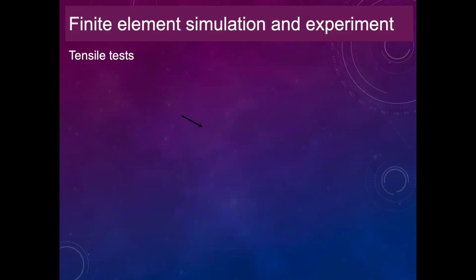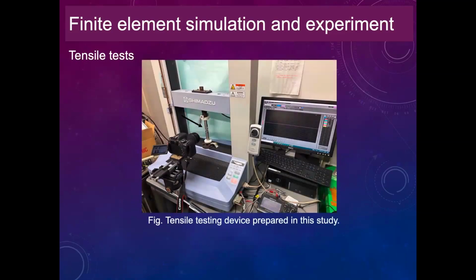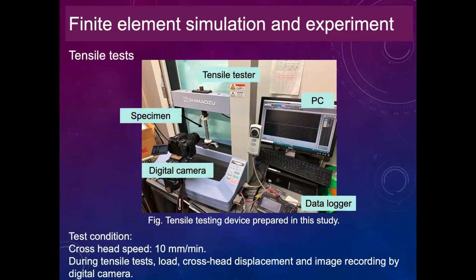In accordance with the FEM result, we conducted the tensile test for the actual CT specimen, which was printed by the 3D printer. This is the tensile testing device prepared in this study. Here, the CT specimen was set around here, and during the tensile test, the specimen fracture was continuously observed using a digital camera, and the load cell and cross-head displacement were recorded continuously into the data logger as shown here. As the test condition, the cross-head speed was set to 10 millimeter per minute. That is a very low speed in comparison with the conventional speed of the tensile test.